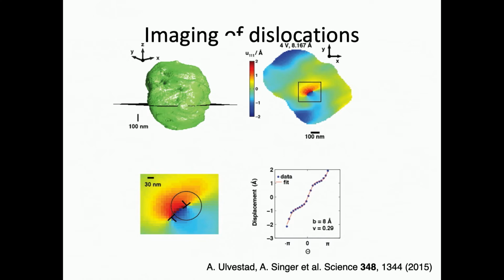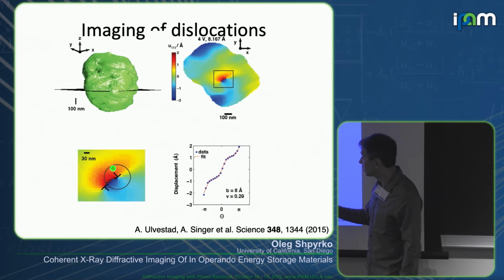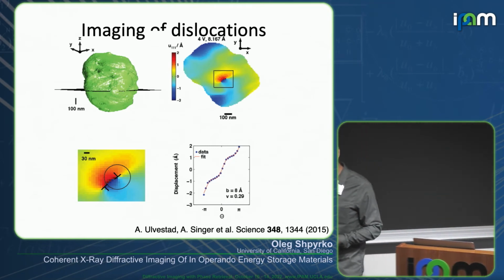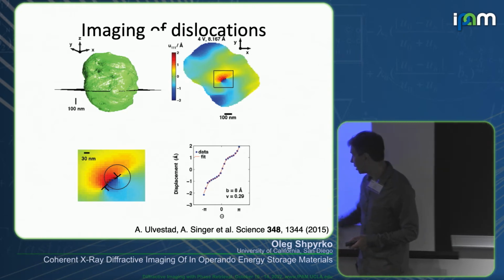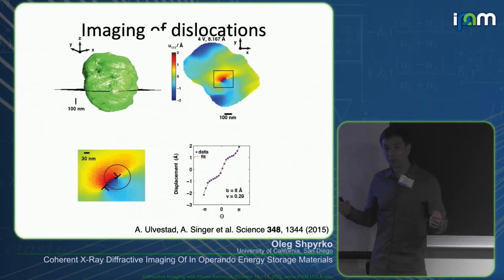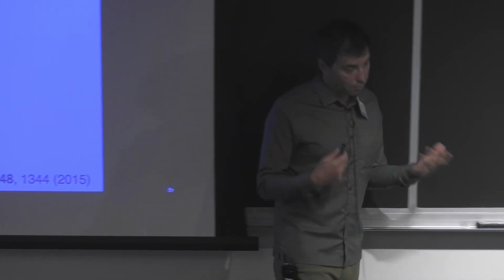So effectively, it's also a measure of elastic properties of the crystal around that dislocation. There is a weird thing that happened there that I'll admit I don't fully understand, which is that at some points this parameter becomes negative, which means that when you push on something, instead of compressing it, it expands. There are predictions about this kind of material, but it's too exotic for me to really speculate about exactly the origin of that. And it only exists in certain parts of the charge-discharge cycle.